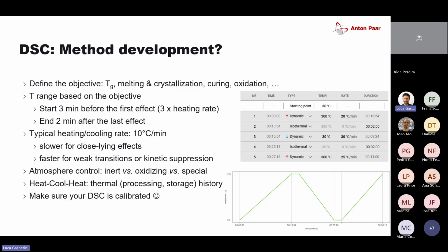And then you define the temperature range of the measurement based on the objective, of course. So if I measured a sample today that I was provided by the local guys here from PIEP, and they said, this is a polylactic acid, I was like, okay, good. So it should have a glass transition below 100, then it should melt. So I'm good to go to about 200 degrees. I don't necessarily need to heat the sample up to 600 or 700 degrees, because I know that it would decompose, but that's not my objective. So I reduced the temperature range to something that was making sense to me.